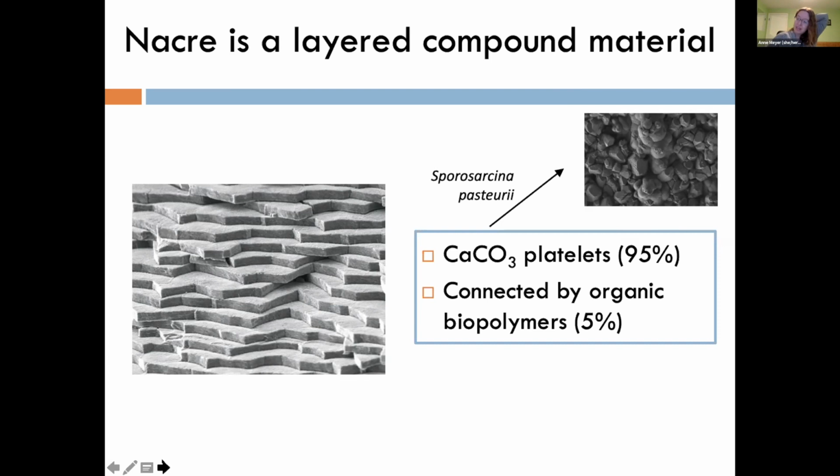It has really high levels of an enzyme called urease. What this means is that if you're growing the bacteria and you add some urea, a common byproduct of animal life, it will break the urea down into ammonia that makes the pH go higher and higher. When you get to pH 9.5 or 10, then you have spontaneous crystallization of calcium carbonate, right?